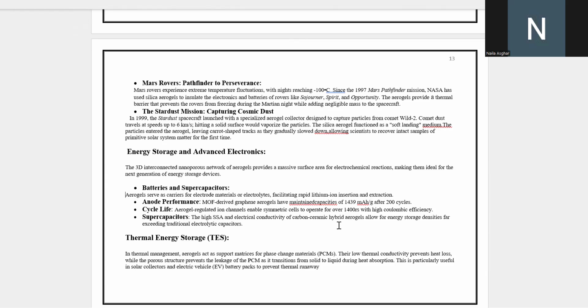Metal organic framework derived graphene aerogels have maintained capacities of 1439 mAh per gram after 200 cycles. Aerogel-regulated ion channels enable symmetric cells to operate for over 1400 hours with high Coulombic efficiency. The high electrical conductivity of carbon ceramic hybrid aerogels allows for supercapacitor energy storage densities far exceeding traditional electrolytic capacitors.